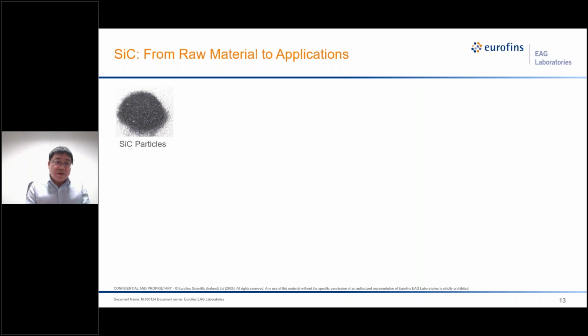So how to make the silicon carbide? The silicon carbide is grown from particles because there is no solution phase for silicon carbide. Physical vapor transport is the method we use to grow it. The temperature is usually 2,500 Celsius. Precise control of the temperature is the key for the specific crystal growth. So the growth rate is much slower. Basically, it's less than 1 millimeter per hour. So this is very different from the float-zone silicon. Float-zone silicon will grow at a low temperature, around 1400, and the growth rate is about several millimeters per minute.